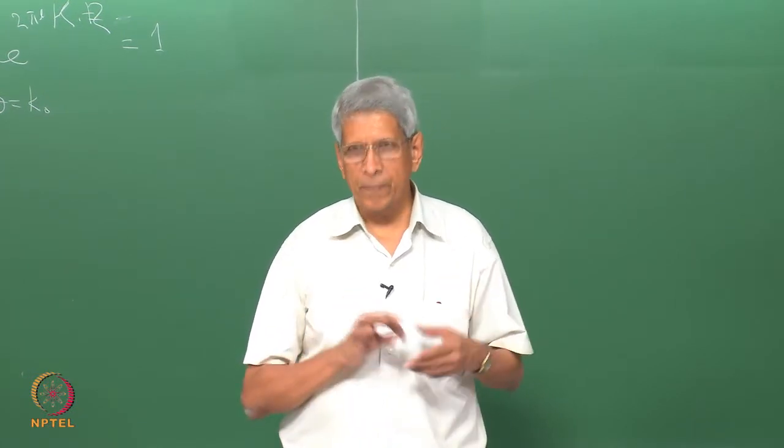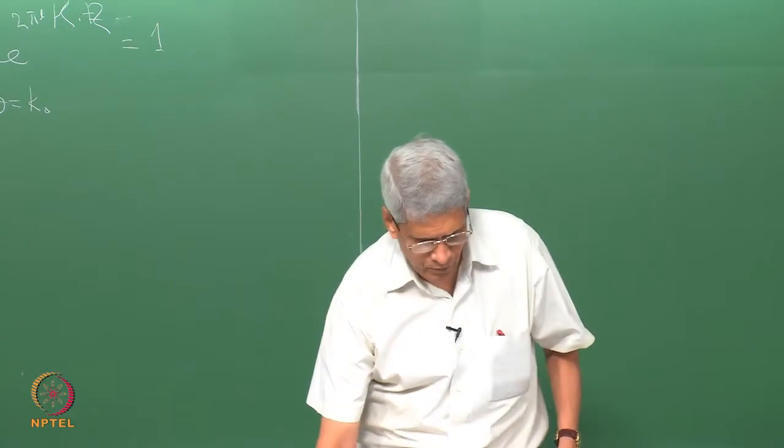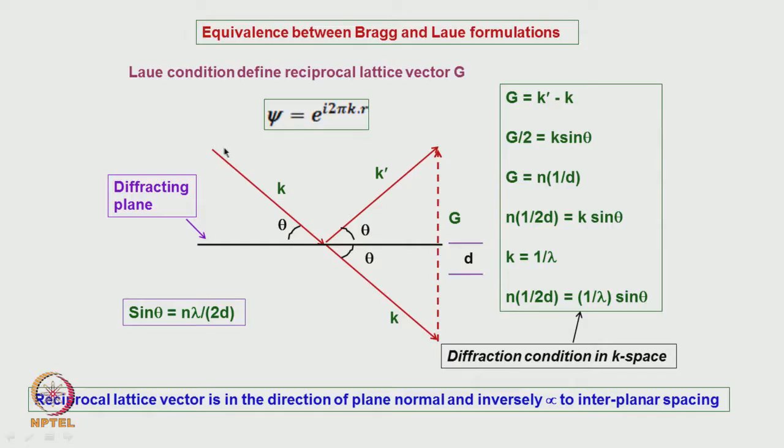You understand that? Okay. That is, if this is the incident beam and this is the vector k and this is k dash, the scattered vector, and since the magnitude remains the same for both of them, with respect to this point as the center, if you try to draw, in this particular case it will be a circle, in 3 dimensions it is going to be a sphere. That sphere we call the Ewald sphere.